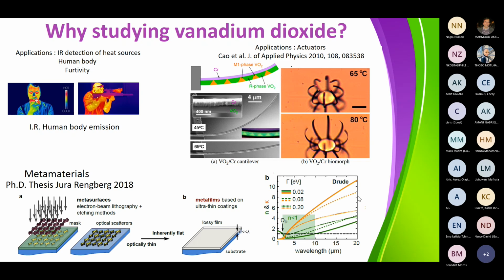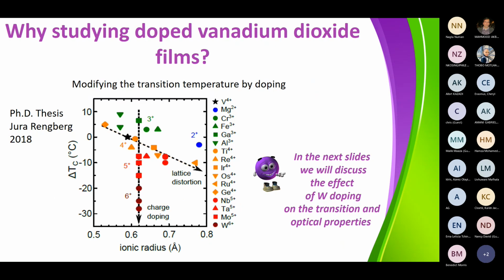And additionally, it can be used as metamaterials. Metamaterials are interesting materials because they can make the index of refraction below 1 and negative. Typically here you see in this case, you can go negative in the index of refraction. And so, of course, vanadium dioxide is a very interesting material, but the key point is that it's interesting as a pure material at 68 degrees. But what we want to do is really to be able to use it at a lower temperature, close to room temperature. So how do we do that?